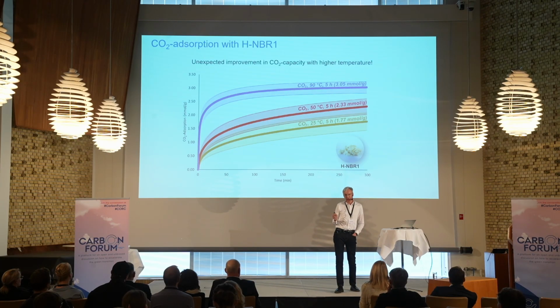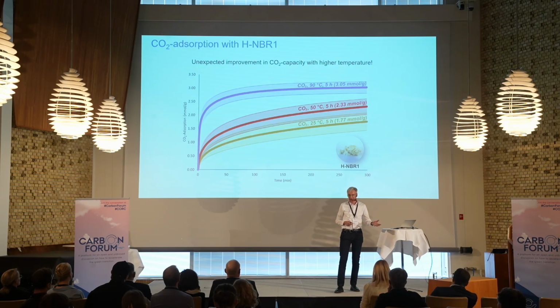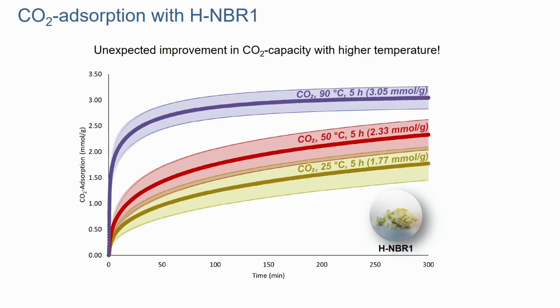When Simon was looking at this, we had a suspicion these materials were not going to be very good because they're not porous, okay? In other words, there are no cavities for the CO2 to go into. And sure enough, at 100% CO2, 25 degrees and 50 degrees, the capacity for CO2 capture is not that great. But what was really cool about this material is that its capacity increased considerably at 90 degrees. And 90 degrees is a typical flue gas temperature for certain power plants. So that was pretty cool.